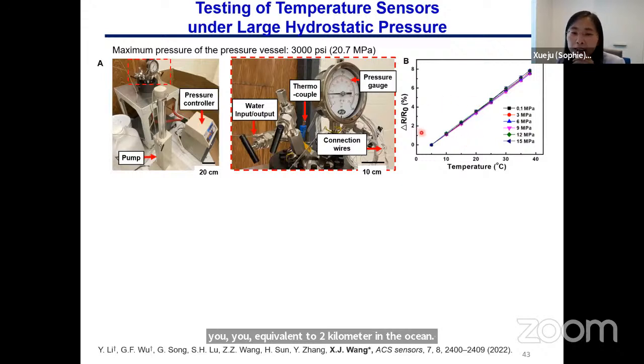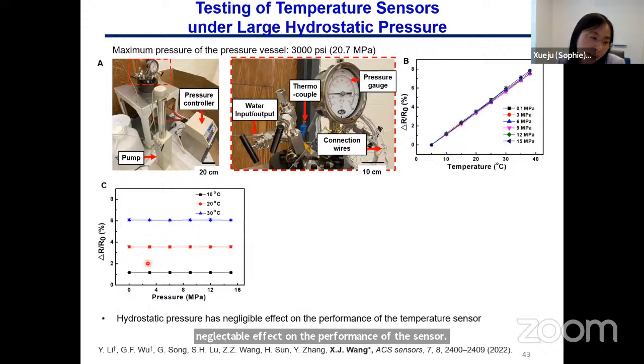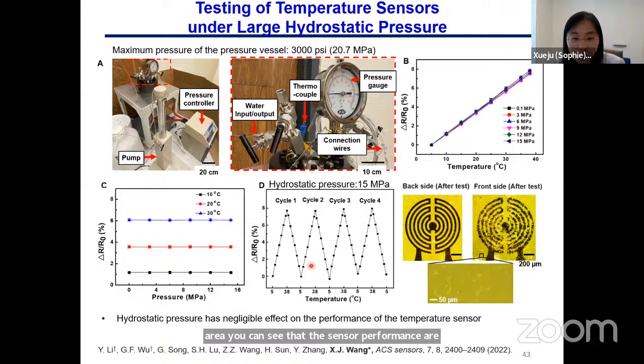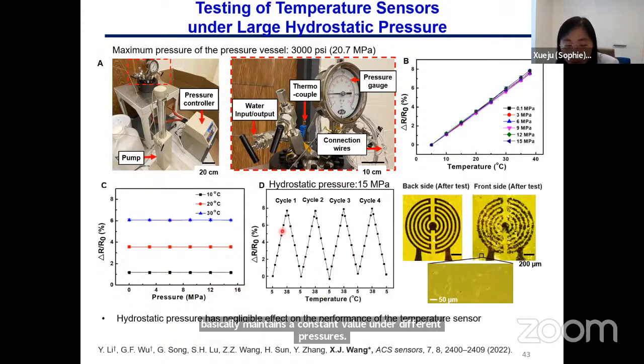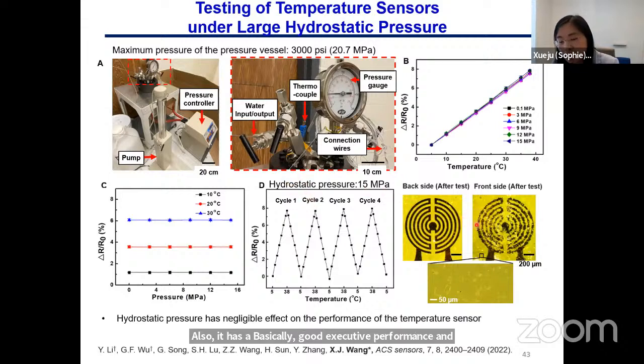We can see that when the sensor is tested under a hydrostatic pressure from 0.1 megapascal to 15 megapascal, which corresponds to 1.5 kilometers in the ocean, it still maintains the linear relationship between the response of the sensor and the temperature. Also, the hydrostatic pressure has a negligible effect on the performance of the sensor, which is further indicated in this plot, where you can see that the sensor performance maintains a constant value under different pressures. Also, it has good cyclic performance under hydrostatic pressure. In addition, the morphology of the sensor, including the backside and the front side, has negligible changes after the testing.